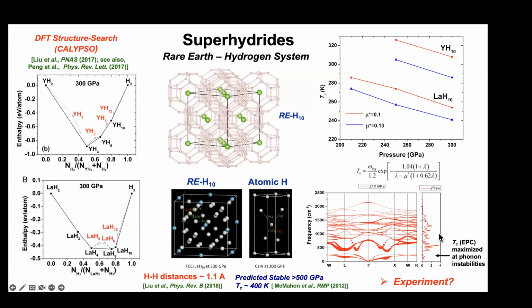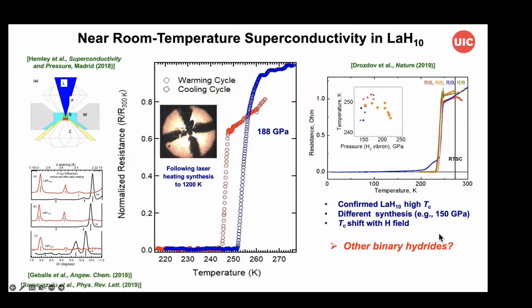So what about the experimental confirmation of this? We conducted a series of experiments right after these calculations. First of all, we targeted the pressure range that the theory predicted for the stability of the decahydrides for lanthanum, yttrium. Yttrium was much more difficult, but lanthanum was quite forgiving. And in the initial experiments, we found it was very easy to synthesize the lanthanum decahydride.